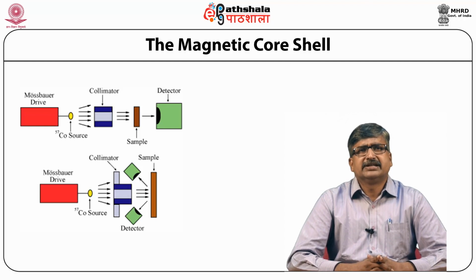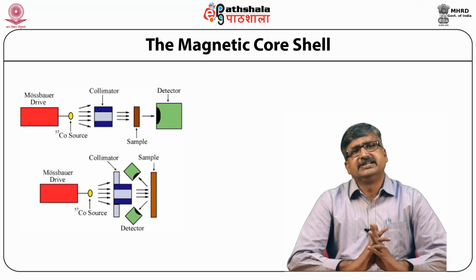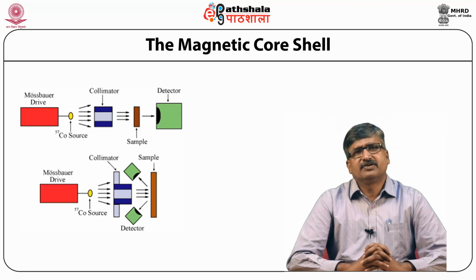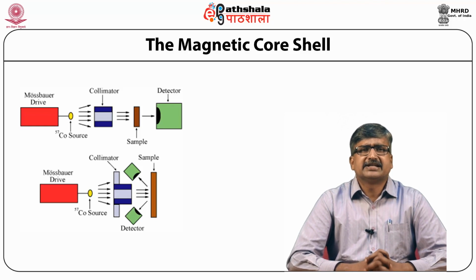It is paramagnetic above 250 degrees Celsius and antiferromagnetic below this Néel temperature. When the size of NiO particles is reduced below 10 nanometers, it exhibits a huge increase in magnetic susceptibility below the Néel temperature and so superparamagnetic behavior at room temperature.